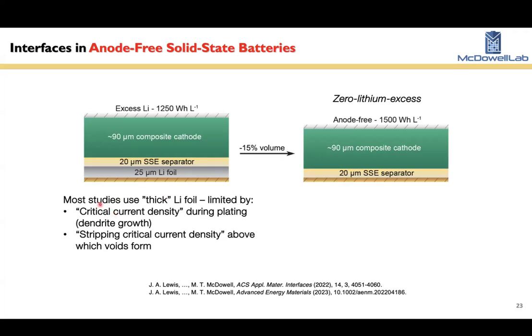And we know that these sorts of cells are limited by the critical current density during plating that governs dendrite growth, and then the stripping critical current density.